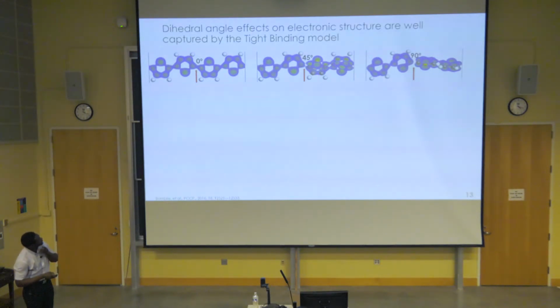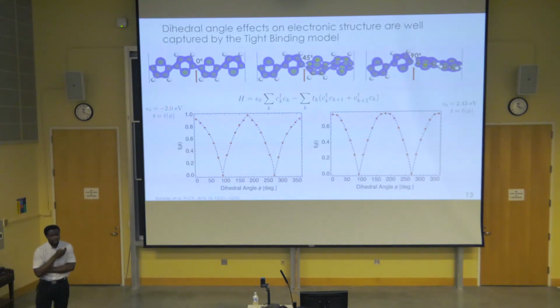And what you notice is as the dihedral angle is distorted, we are breaking conjugation. And by the time we reach a dihedral angle of 90 degrees, we have completely destroyed the electronic pathway for conduction. So we captured this in our tight binding model, we have determined how the parameters that control the hopping of charge carriers from one side to another depend on dihedral angle.